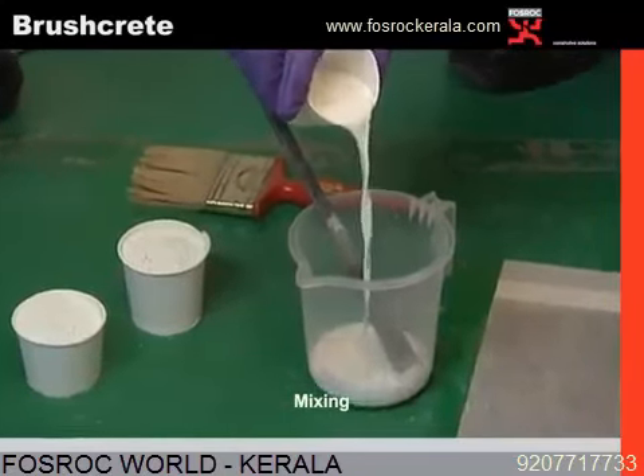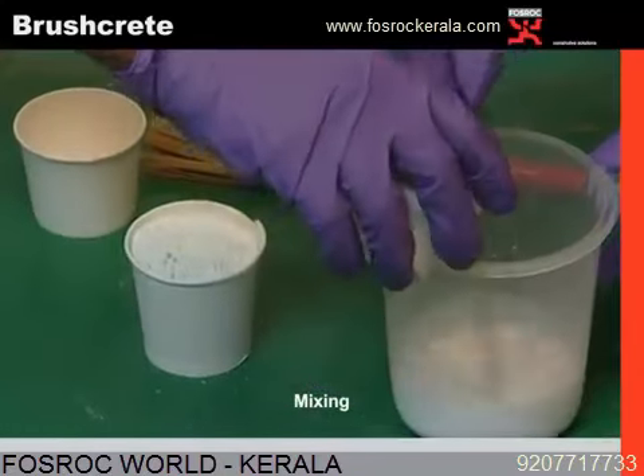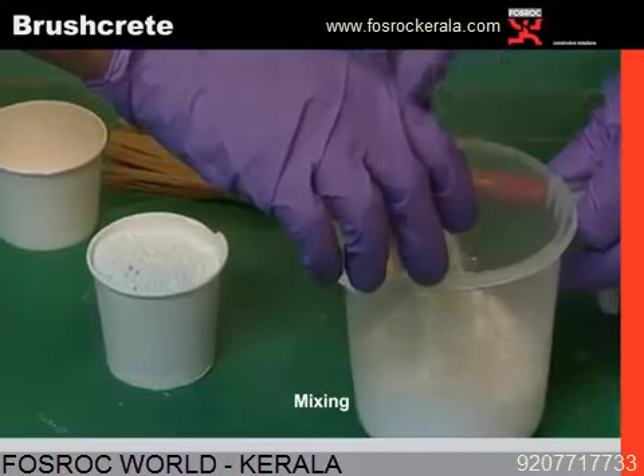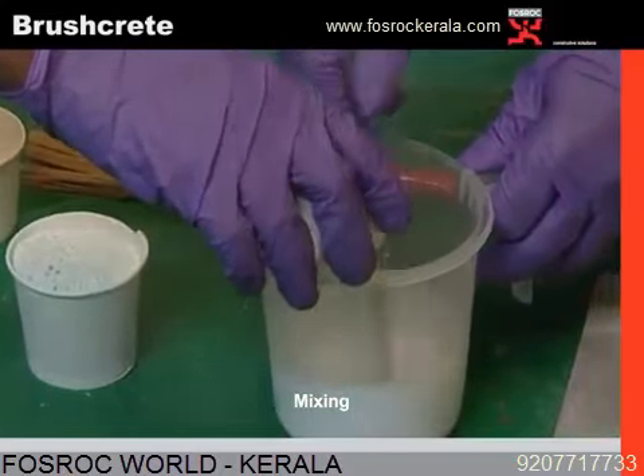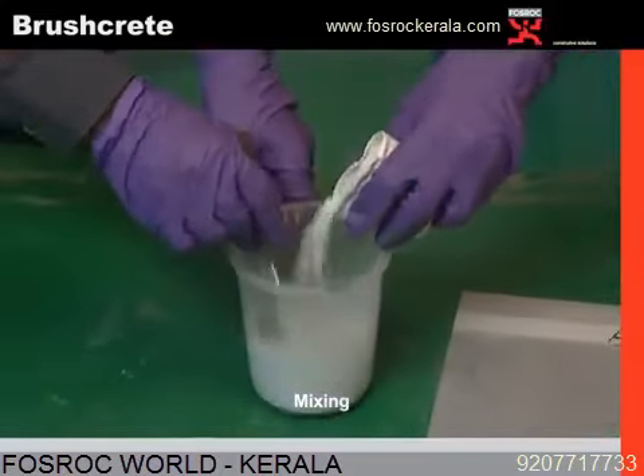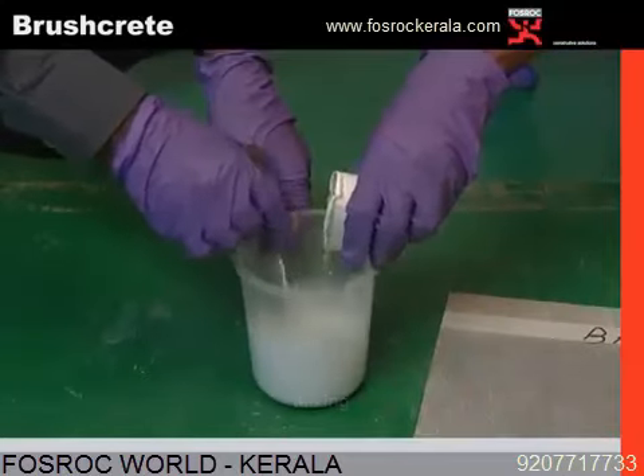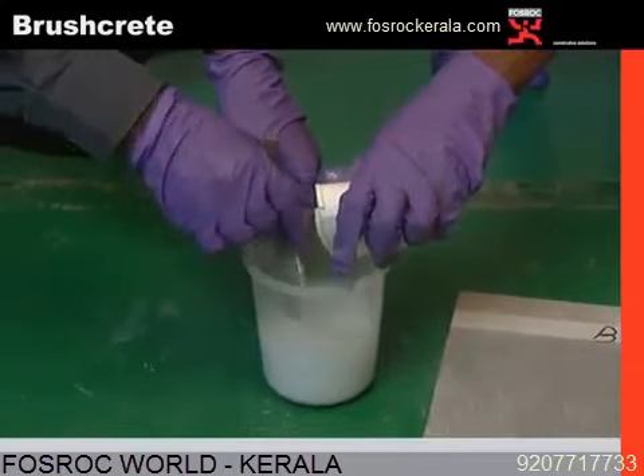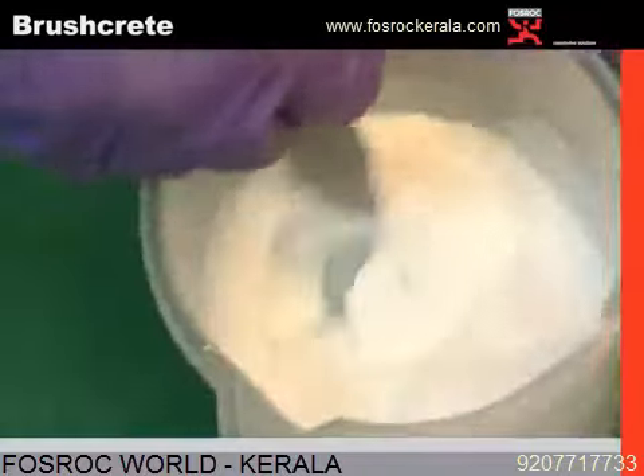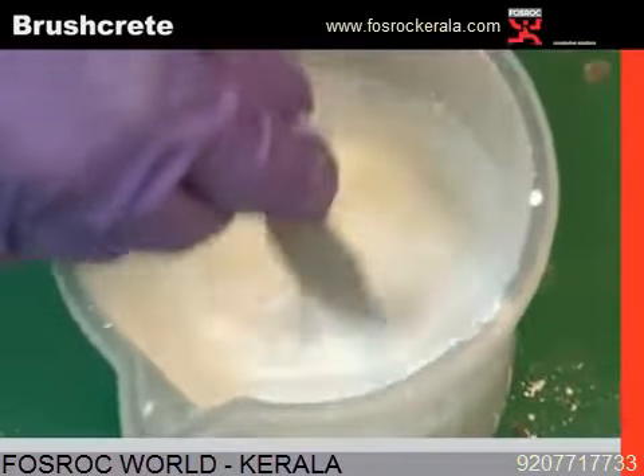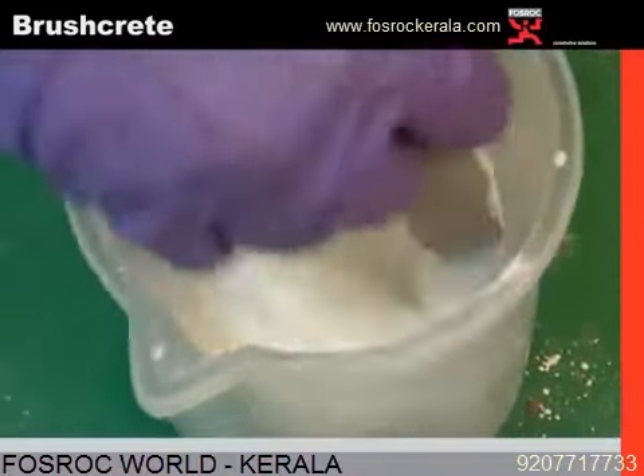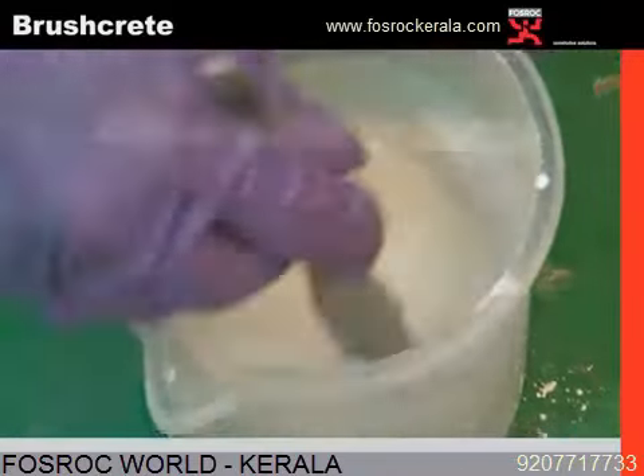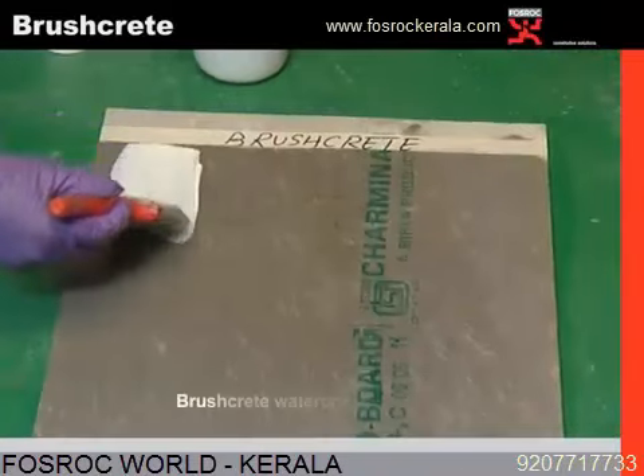For preparing, add the polymer, mix cement as shown. If a white color coating is required, we can use white cement, or grey cement can also be used in place of white cement. Then the mixing is done as seen. Once mixed, this mixture is then brush applied on the prepared surface as shown.